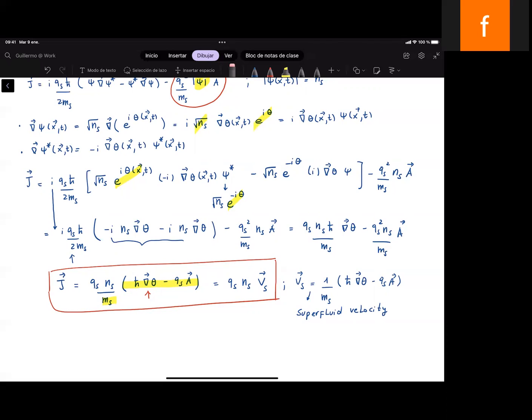All on the surface, because if you go deep into the superconductor, we will prove that this density current also decays exponentially, and there is a characteristic length, which is the London penetration depth. So the superconducting current always lives on the surface of the superconductor. Okay, thank you. You're welcome. We will show this with an example, and you can really see that this superconducting density current decays exponentially.